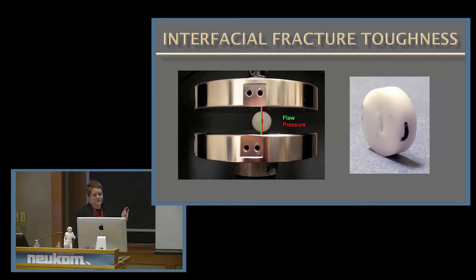There are these little discs of Carrara marble, and they're called Brazil discs. They have a little elliptical hole that sort of forces a flaw. It's like a built-in flaw in the specimen. And that forces a crack to occur all from the same central location, as opposed to depending on whatever random features might be found in the stone. So these specimens were glued together with various different adhesives, and then they were tested on an Instron. What you're looking at, the shiny parts, is an Instron machine that pushes down and takes measurements on the force. And so what we did was test it with the elliptical hole at various positions, each specimen placed at a different position.